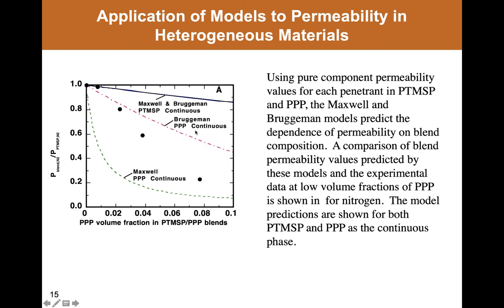And the red dashed line is showing the Bruggeman model for the case where now the polyphenyl propyne is continuous, and the Maxwell model for that case is shown here. And so what these data start to tell us is that even at very low volume fractions, there is an inversion in the phase of this heterogeneous material, and the polyphenyl propyne actually starts to become the continuous phase.